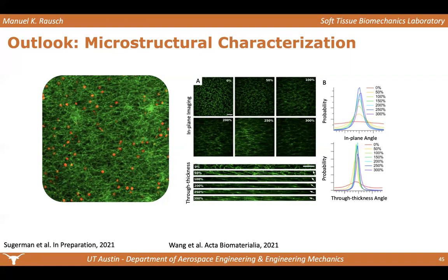And so one of the things we started doing is actually we take the blood clot. And what's very cool is you can take the blood, and it consists essentially of 3 things: the fibrin, the platelets, and the red blood cells. And we can actually put them in a centrifuge, spin them down, separate the 3, and then we can fluorescently label the fibrinogen or the fibrin, and fluorescently label the red blood cells and the platelets, we can put them back together and make a blood clot out of it. And then we can look at it, in this case, under a 2-photon microscope.